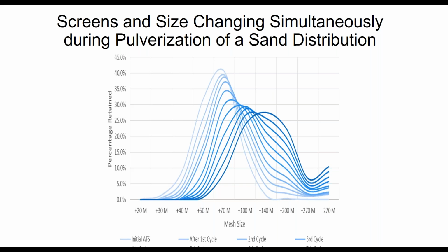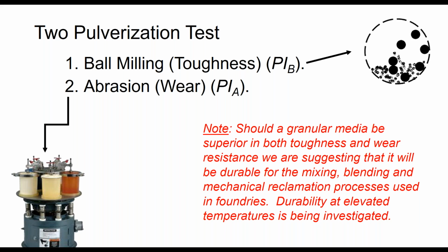But should we look at a distribution, what happens is that we have the particle size change, especially the larger particles, and we have the distribution change at the same time. And because of that, it's hard to compare. So what I'm trying to suggest is that the smaller particles are protected. If we look at the distribution after impact and after abrasive wear, like I am depicting on this slide, such as a ball mill test or abrasion, the smaller particles appears as there was no effect.